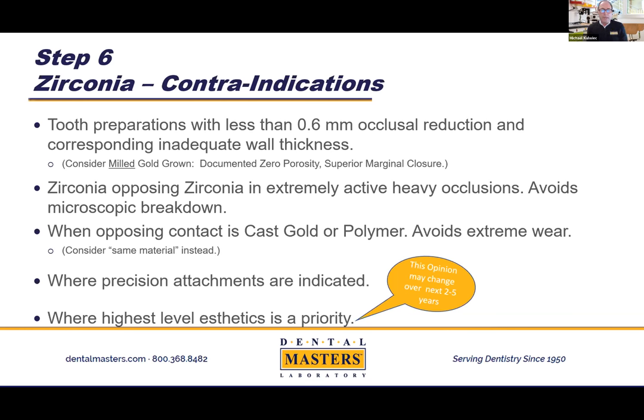We mill them. There's documented studies underlining the fact that a milled gold crown is, in essence, a zero porosity crown. And done properly by both the mill process and the laboratory will lead to superior marginal closure. Those are pluses relative to the use of cast gold.